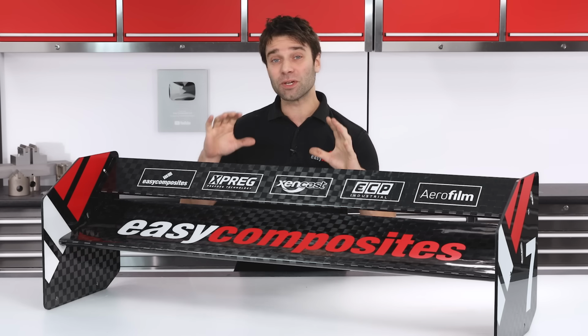Vacuum bonding panels like this does not require full vacuum. In fact, using full vacuum can cause problems. The additional pressure would squeeze all of the adhesive out from the edge of the cells, and also the additional movement of air during evacuation and potential for foaming the adhesive mean that regulating the vacuum to around 20% of full is preferable. I've repeated the exact same process on the second panel, so I can now leave these to cure under vacuum for around 6 hours.